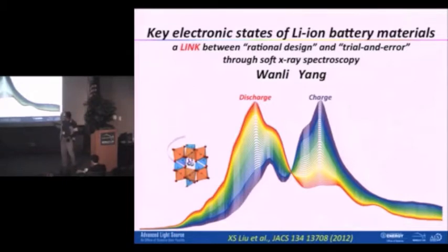The valency is the most obvious, of course, and then the detailed structure tells you the very local lattice distortion during this charge and discharge process, and other details tell you about the phase transformation. When you have lithium in and out, you have a lithium phase or a non-lithium phase, and how these two phases evolve and transform. You can get all this information relevant to battery performance with soft X-ray spectroscopy.